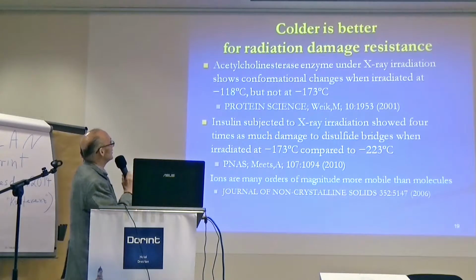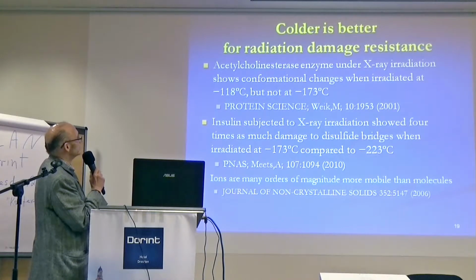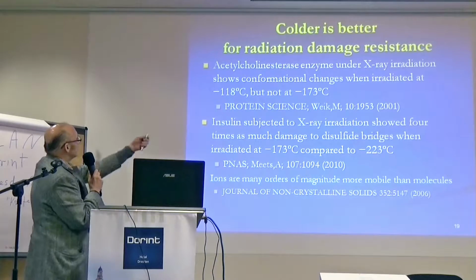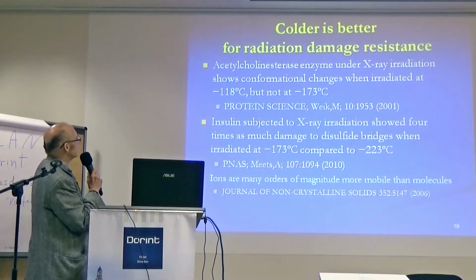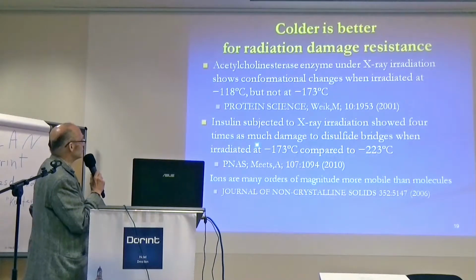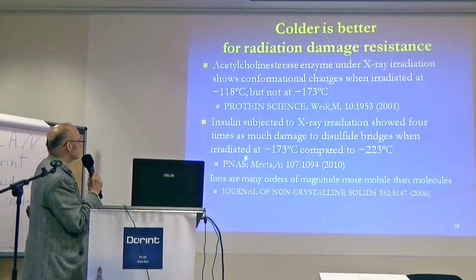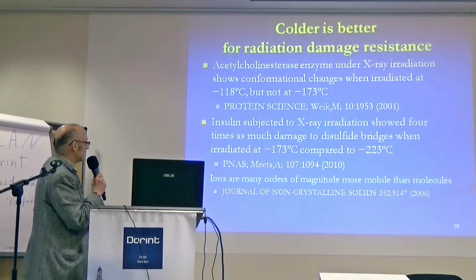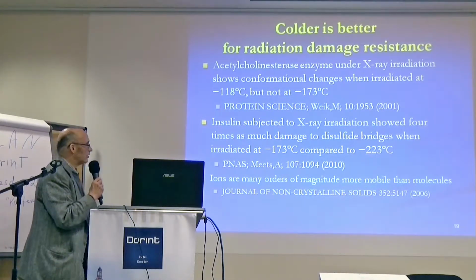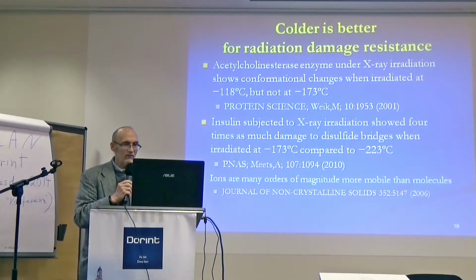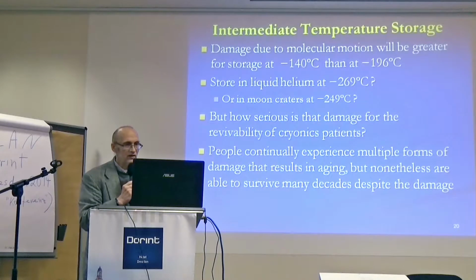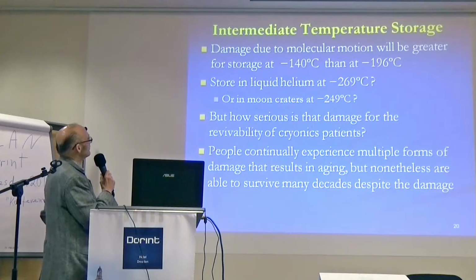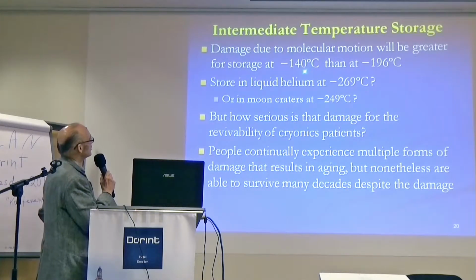Just an aside, other things to worry about. It is better to be colder to avoid radiation damage. The acetylcholinesterase enzyme under X-ray radiation shows conformational changes when irradiated at minus 118 degrees Celsius, but not at minus 173. And insulin subjected to X-ray radiation suffers 4 times as much damage due to disulfide bonds when irradiated at minus 173 degrees Celsius compared to minus 223. And ions are many orders of magnitude more mobile than molecules. And we still have ions, even though we're in a solid cryogenic state. So we get greater molecular motion at minus 140 than minus 196.